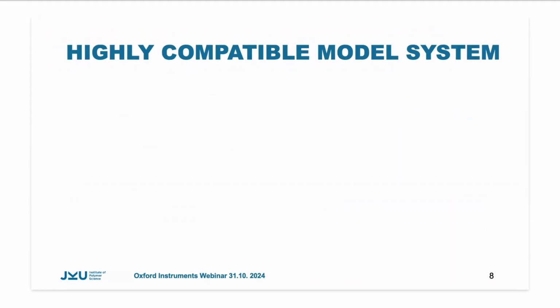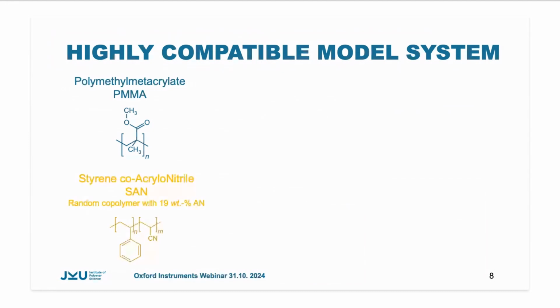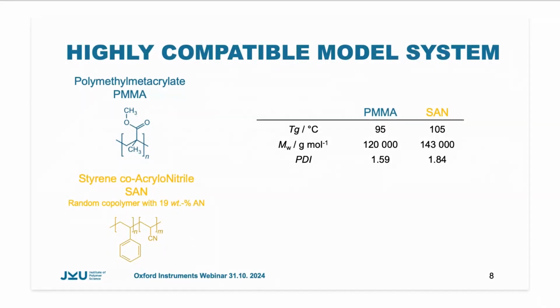Our highly compatible model system consists of PMMA on one hand and styrene co-acrylonitrile, a random copolymer which contains 19% of acrylonitrile, on the other hand. Both polymers are amorphous polymers. They have a comparable glass transition temperature of 95 or 105 degrees. We choose samples which have similar molecular weight and a similar molecular weight distribution to avoid any further influence of different molecular weights.